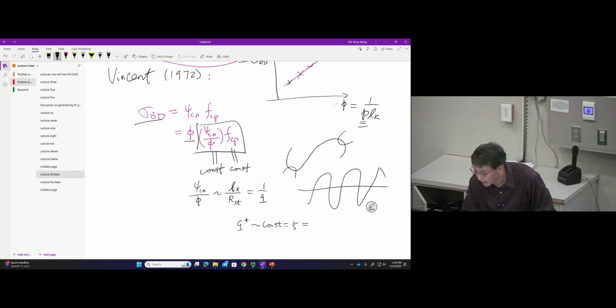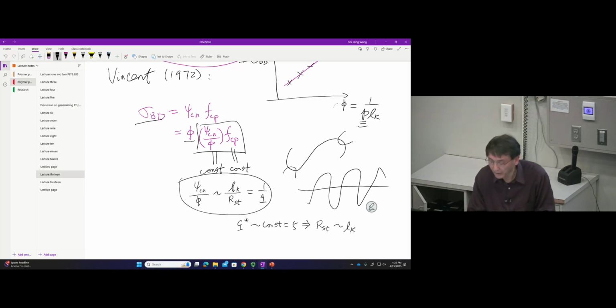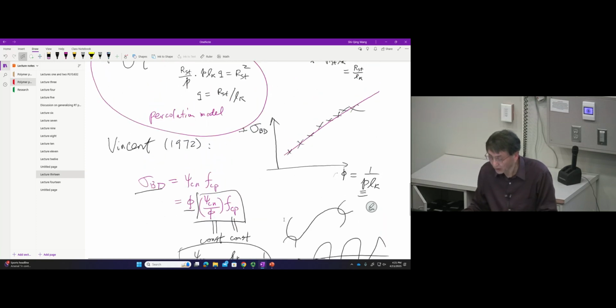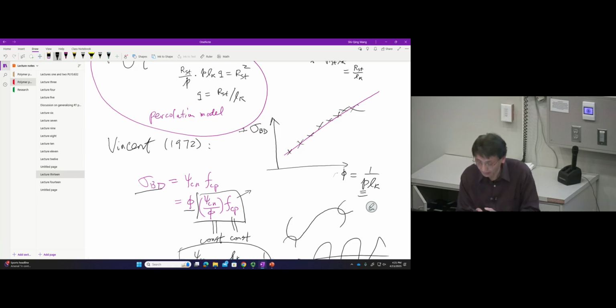And this suggests that the strand size is proportional to the Kuhn length. In other words, this number, by the percolation model, by construction is a constant. And the more striking part is really for you to imagine that this pull-out force is constant. Is that possible? Well, we don't have a theory for that.